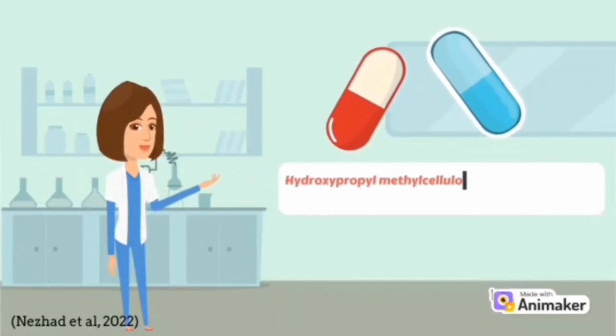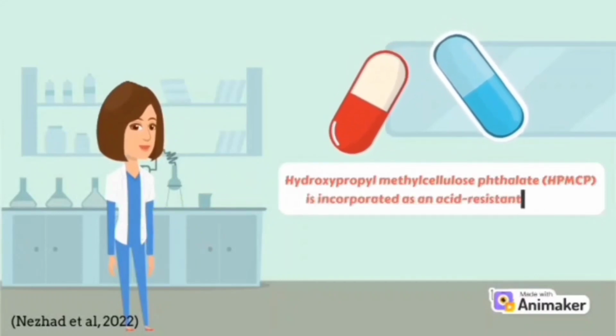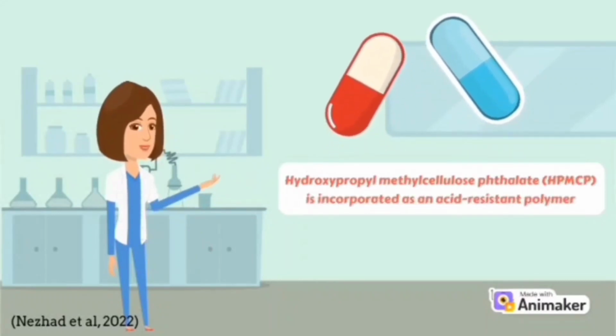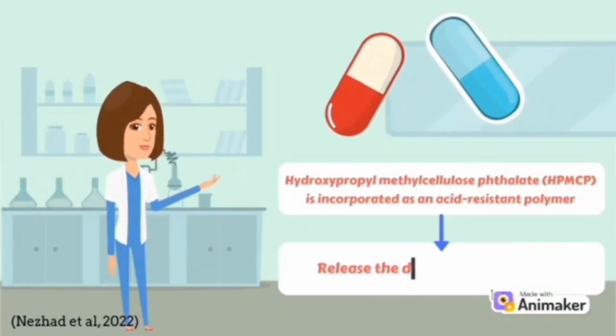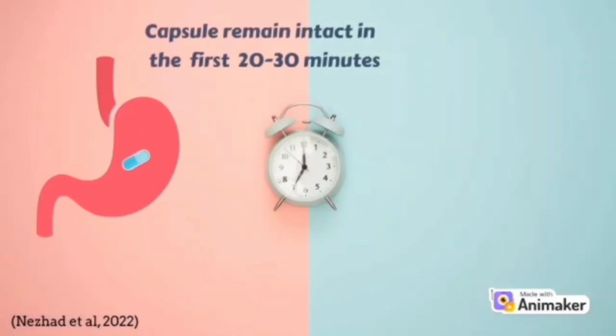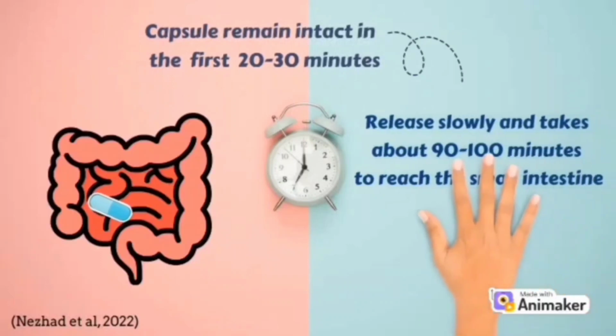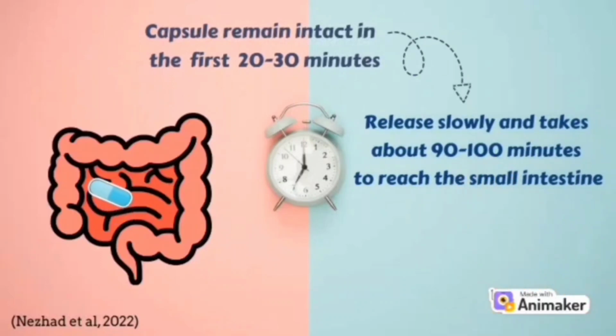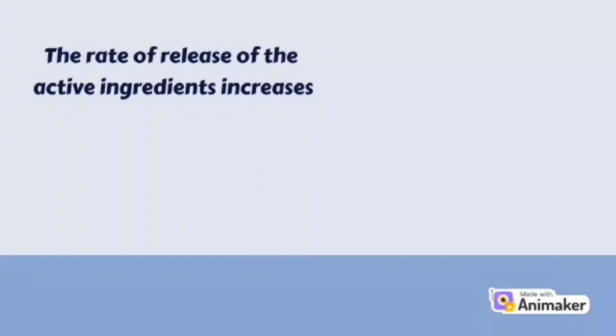The hard gelatin capsule is produced by incorporating HPMCP, which is an acid-resistant polymer that allows the capsule to remain unchanged in acidic environment and only release its content when the capsule reaches the small intestine. The capsule remains intact for about 20 to 30 minutes after entering the stomach. After that, it will slowly release and reach the small intestine in around 90 to 100 minutes. Once the capsule reaches the small intestine, the rate of release of the active ingredient increases rapidly.